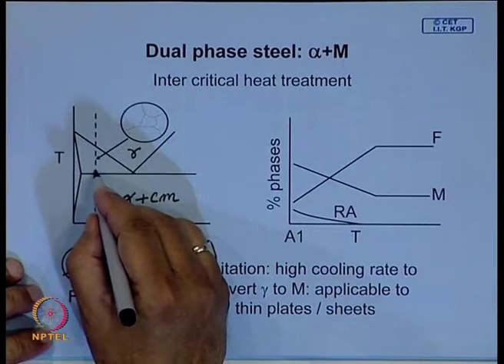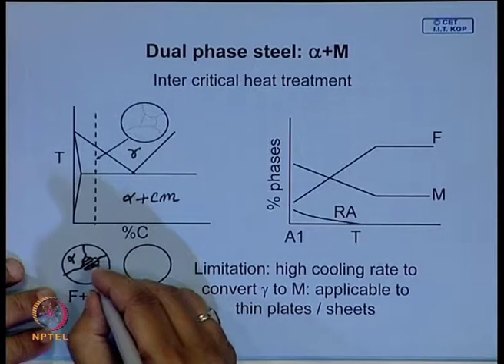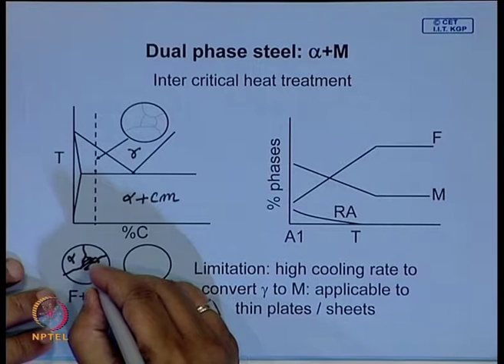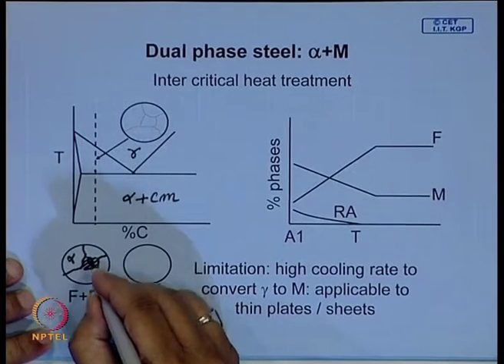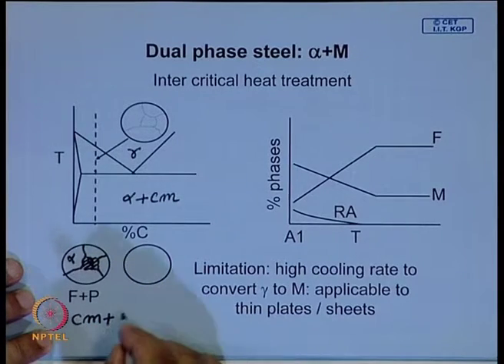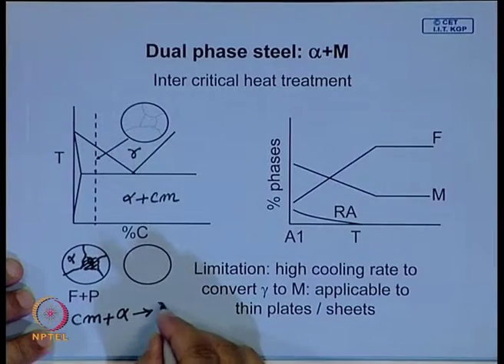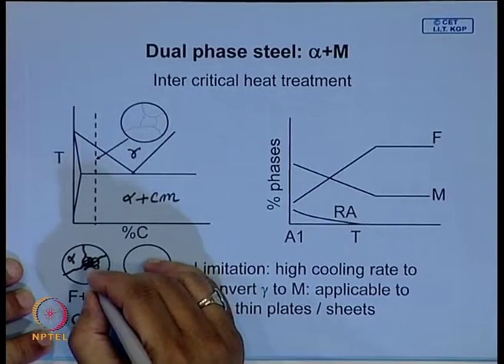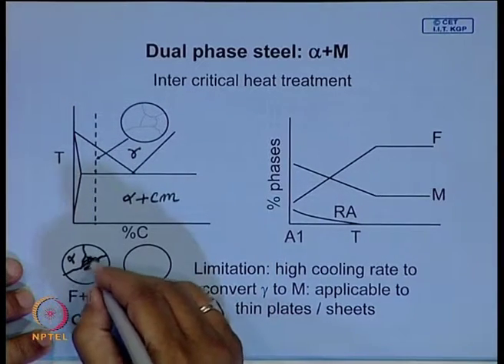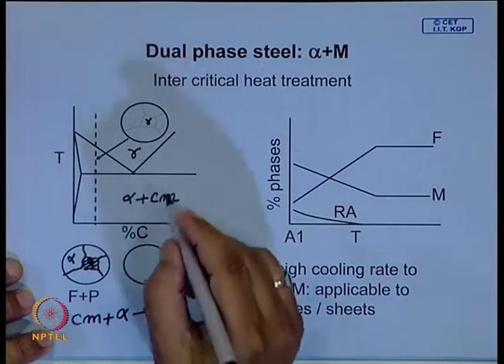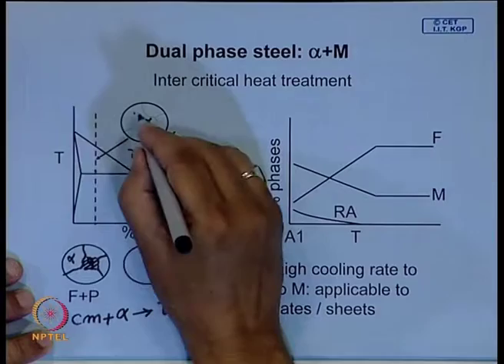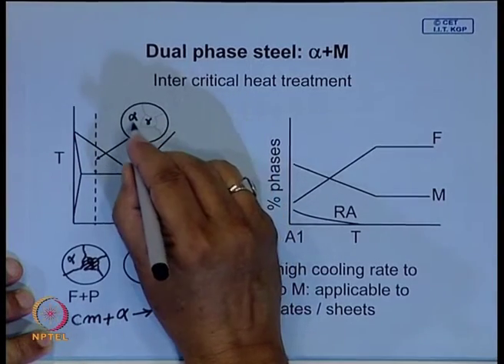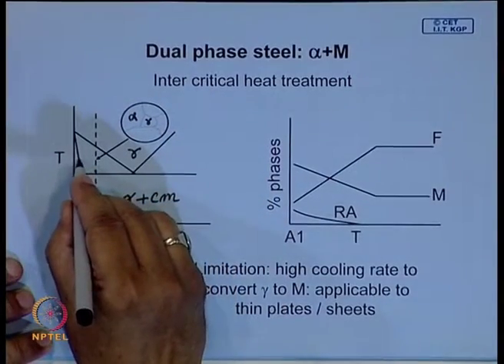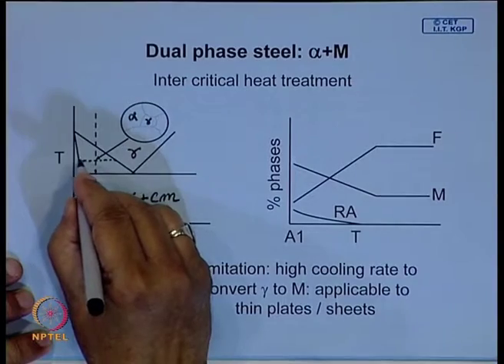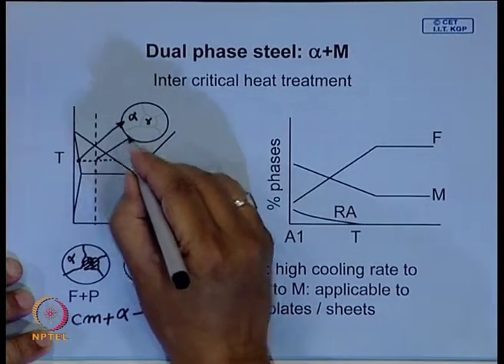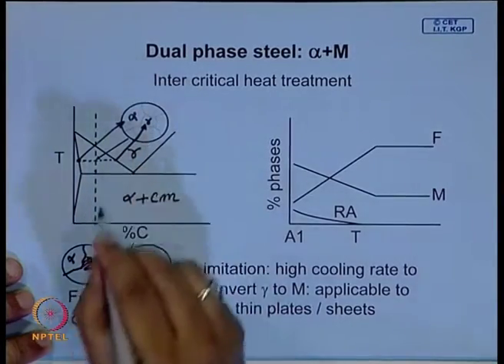Now, when you heat it above this temperature, what happens? In the pearlite, the cementite dissolves, reacts with the neighboring ferrite and gives you austenite. This reaction takes place at these interfaces, and gradually the entire pearlite is converted into austenite. So, what you have now is alpha, that means ferrite, plus austenite. So, it is a duplex structure. You can also see the composition. This point will give the composition of ferrite, and this point will give the composition of austenite.